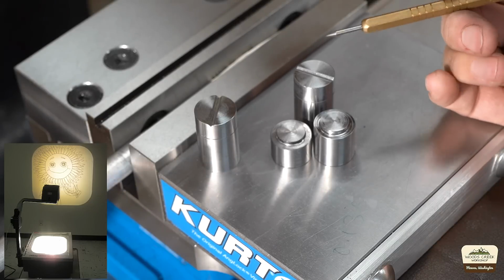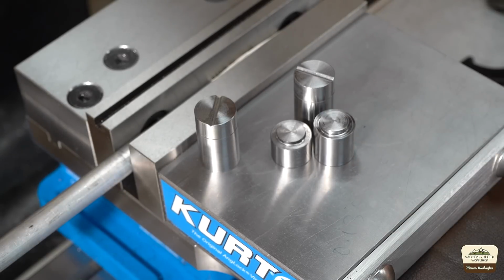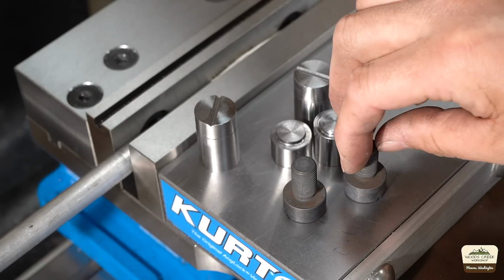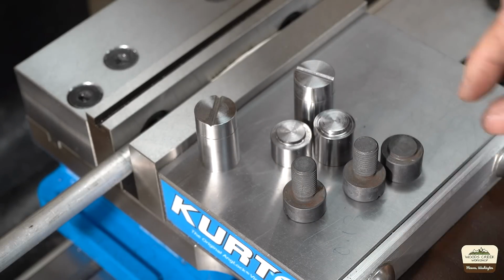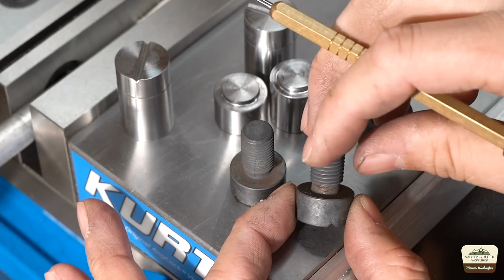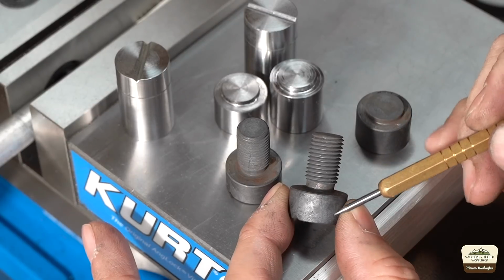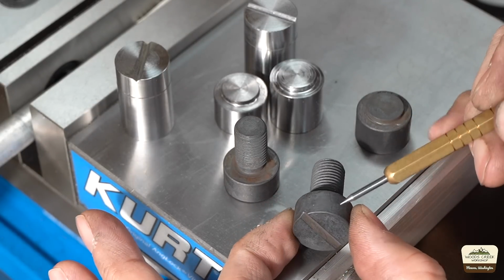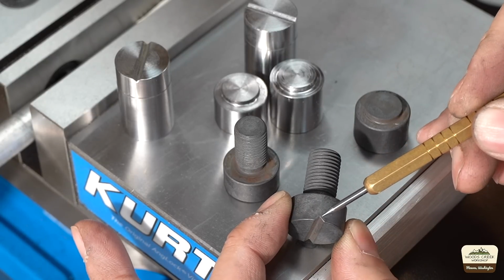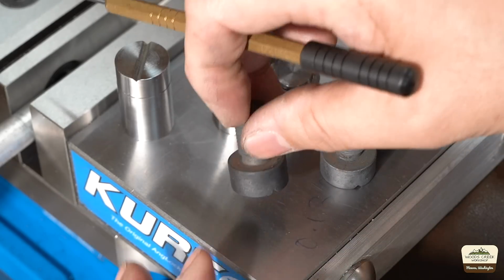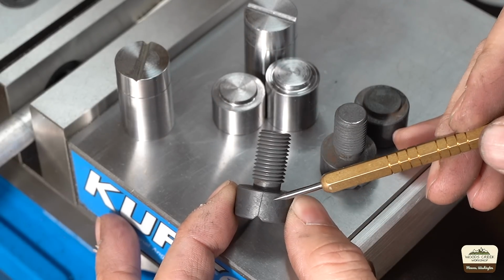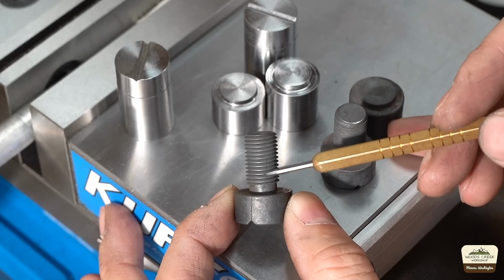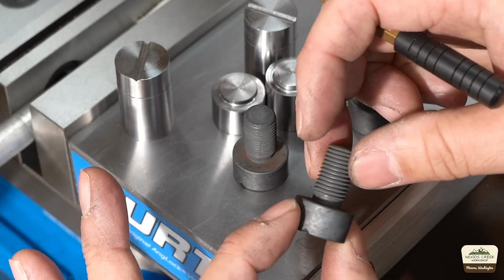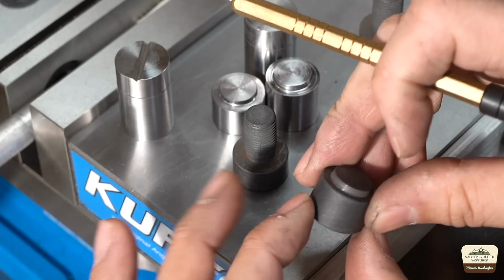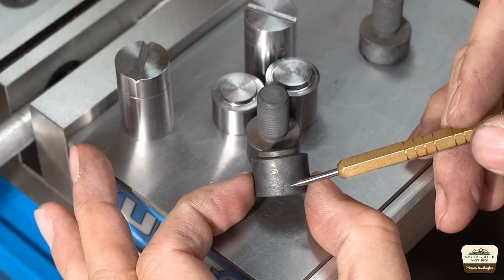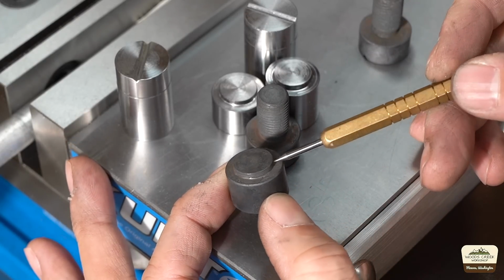For the sake of full transparency, I want to share with you what happened while I was heat treating these parts earlier. These were the original parts that I had made, but during the quenching process, you can see cracks had developed right there, and then it continues on right there. That one's interesting because you would expect the crack to start at a stress point, typically a V notch like that. Exactly where this one started. This one goes straight and then offsets and goes all the way there. And interestingly enough, this piece as well. The crack goes right there, and then it goes along the circumference.